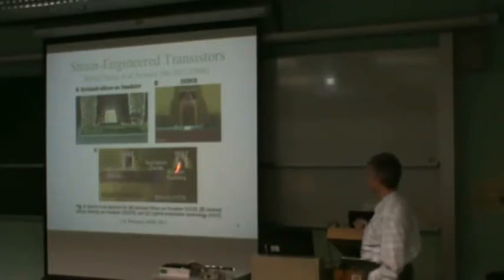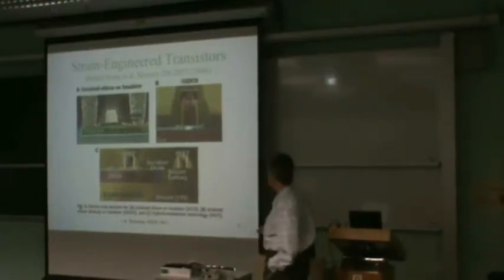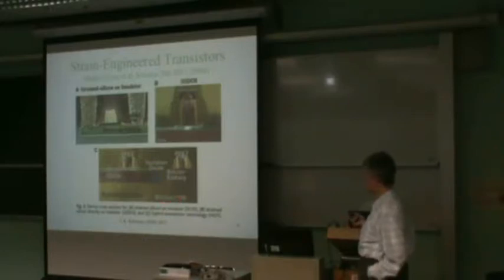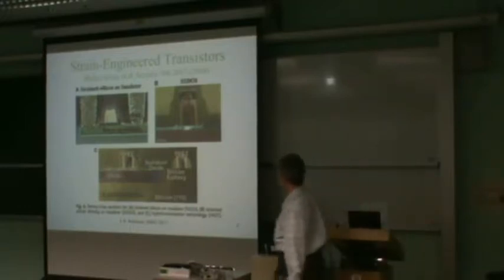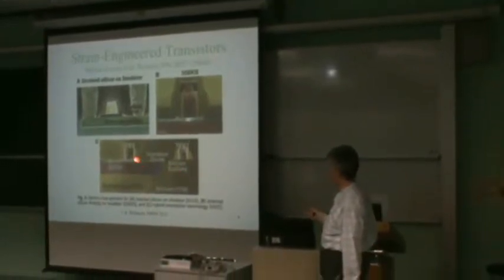and then to make the NFETs in the SOI layer, so that you would pattern these into the thin layer of silicon here with the appropriate stressor, but then to put the PFETs into the 110 material, which is the one where the effective mass can be tailored by stressing the device more effectively, because the piezo coefficient is more favorable for 110 oriented silicon to make the improved hole mobility that's needed for the PFET. So you can make a CMOS device with a gap in the middle where the N and the P components are side by side, but they're actually on different pieces of silicon inside the device.